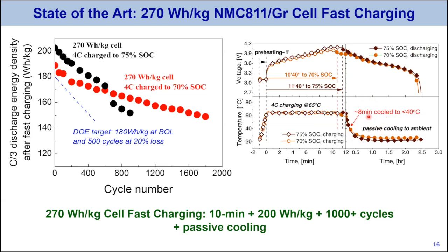Now we can significantly reduce this cooling time from 8 minutes to maybe a couple of minutes if we activate the so-called aspirated air convection. In other words, you open the valve, and while driving on the highway, you get air sucked in to cool the battery pack automatically. So the message can be summarized as: right now we can do around 10 minute fast charging and acquire 200 watt hour per kg, and be able to cycle more than 1,000 times under passive cooling conditions. Okay, so it's all those metrics together.